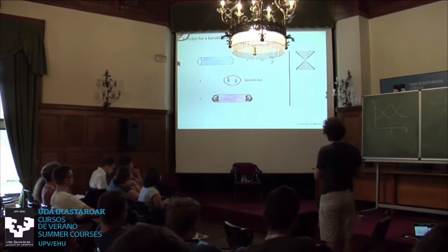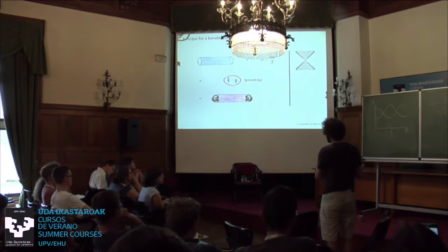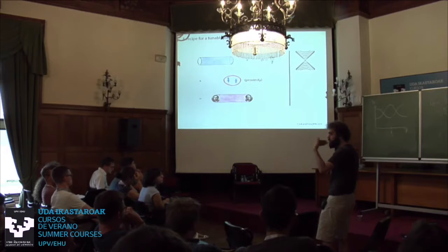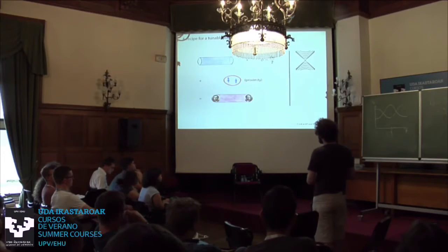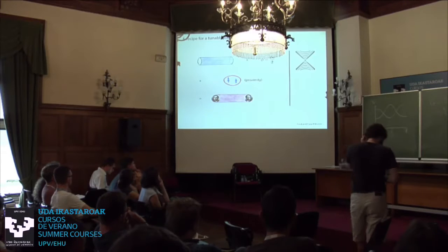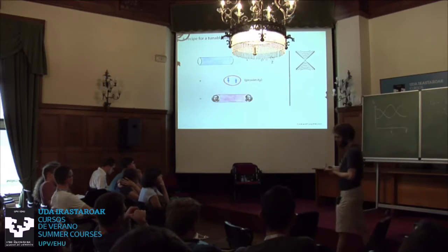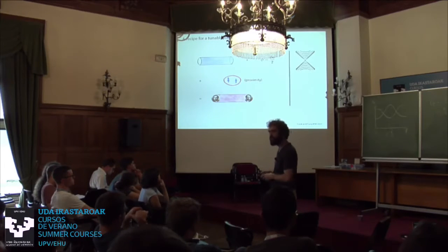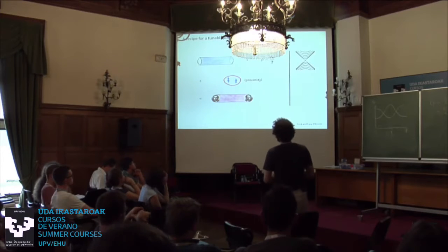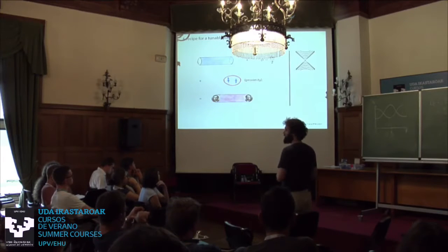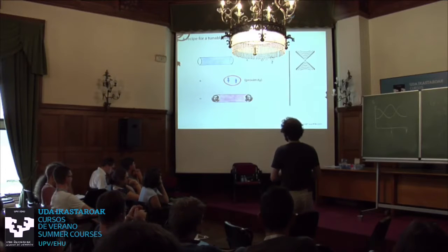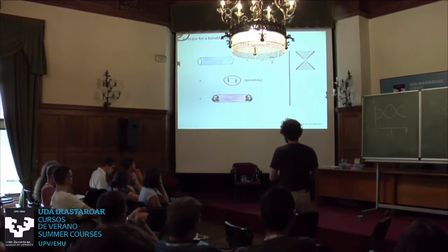The magic of this model is that it doesn't matter. I don't have to do that. I can go higher up in chemical potential, but since I always have an odd number of modes, I always get this guy here, this Majorana. So now I have a way of tunably turning on and off the topological superconductivity. So 0 flux, no Majorana; pi flux, Majorana.